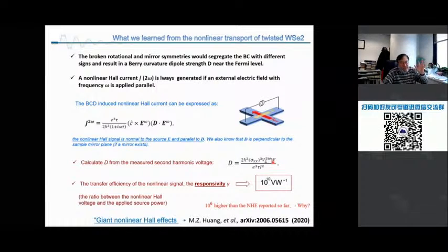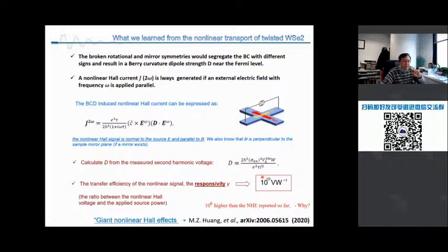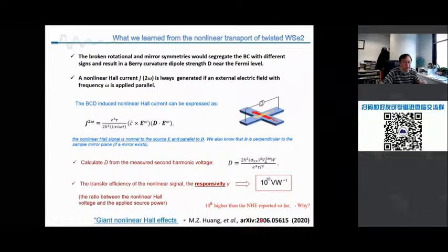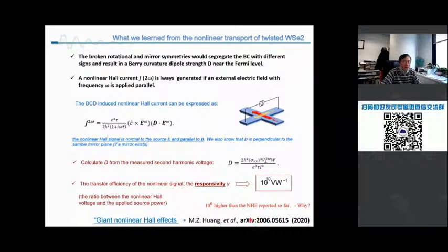All right, so you can estimate the dipole values. The experiment data is roughly around 2 to 3 or 4 nanometers, roughly in that region. There are experimental errors. And then we calculate one important parameter called responsivity. That is the ratio between the nonlinear Hall voltage and the applied source power. That means I apply a very small power. How large is the voltage that I can detect across the sample? Look at here. That number is huge. So we use the term giant nonlinear Hall effect. The paper is not published, but we put it on arXiv. If you want to learn more details, you can take a look at this paper online. And this number is 6 orders of magnitude higher than the so far reported nonlinear Hall effect.